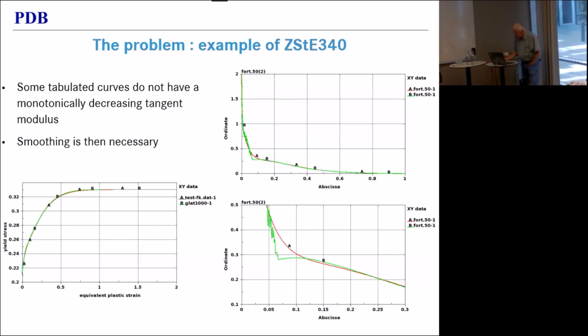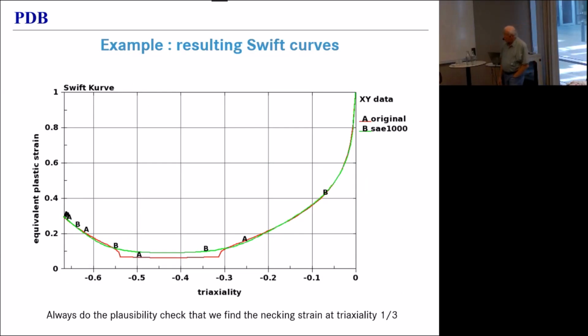Well, the result of that was that with the initial non-smoothed curve, we got this instability curve with a dip in it. If you get that, it's obviously suspect, but you're not sure if it's wrong. But you can very easily verify, because you know for a triaxiality of 1/3, you know the necking strain. So you can check here if you have the right value, and if you don't, there's something wrong. With the smoothed curve, we got the green curve, which not only looks better, but has the right value for uniaxial tension. So it is somewhat sensitive to the smoothness of the yield curve. It's actually very sensitive to the smoothness of the yield curve. And you have to make sure that you don't generate nonsense there.